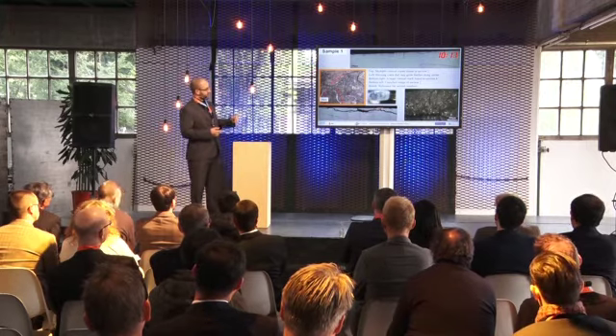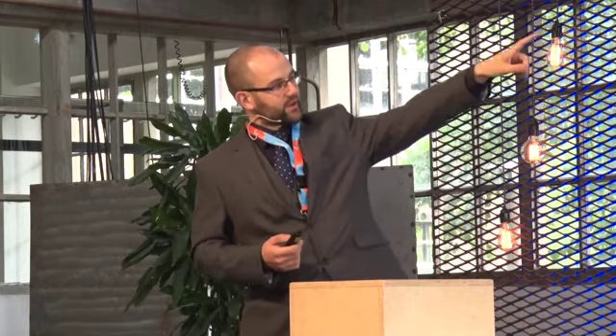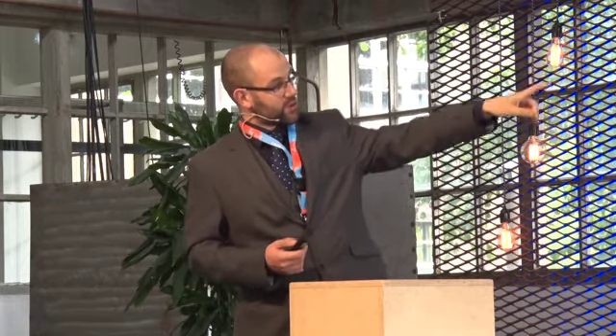The bottom right-hand corner just shows another vertical crack, quite a large one, just on an etched image, and you'll notice the grains are quite highly refined, showing that, again, it has suffered thermal damage. In the bottom, I've highlighted a little area in orange. This is the image that was verified earlier. And you can see where the cracks have started to grow through the structure, and this is 100 times magnification, and you can barely see the grains. So again, it's showing what the thermal damage is doing.